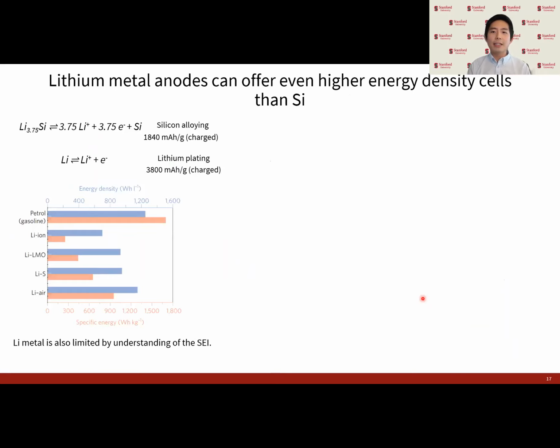Okay, so silicon anodes are already being used in advanced lithium-ion battery chemistries. But beyond silicon, the ultimate anode material is actually elemental lithium or lithium metal. So silicon can store a lot of lithium ions, but it also incorporates some dead weight from the silicon host lattice itself. But for the highest lithium storage capacity, elemental lithium is pretty much impossible to beat.